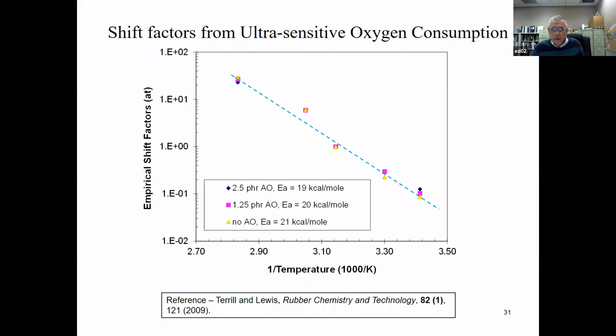Okay. So here is another example of natural rubber compound, and the difference is the AO loading, antioxidant loading, and this shows the oxygen consumption rate shift factors. For no antioxidant, it kind of falls on the Arrhenius line. But if you look closely at low temperature, the one with the antioxidant at 1.25 pHr loading, and the compound with antioxidant loading at 2.5 pHr are deviating and exhibiting some non-Arrhenius behavior down at the low temperature.